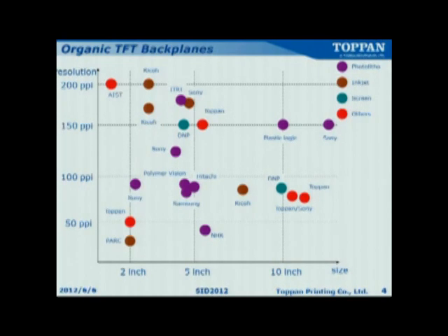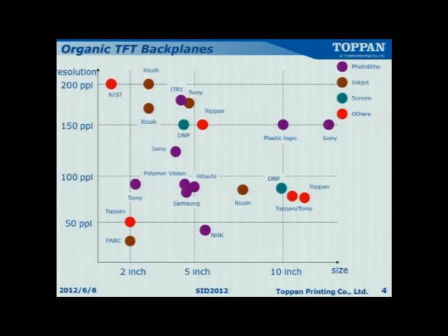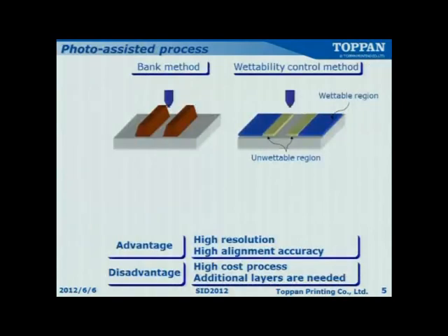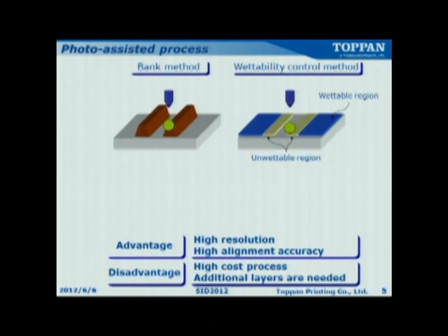And how about inkjet? As you know, it is very difficult to fabricate high-resolution patterns with inkjet process because of large droplet size and spread of low-viscosity ink. To make high-resolution patterns with inkjet, additional processes are needed, such as the bank method or wettability control method. Bank and unwettable regions can prevent ink spreading, so high-resolution patterns can be realized with inkjet process.